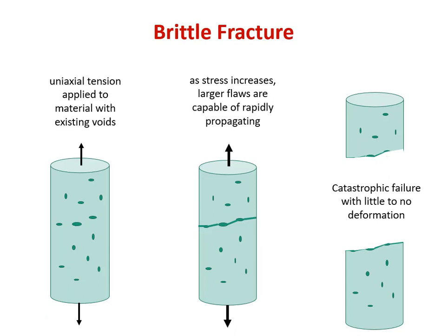we had catastrophic failure with little to no deformation, no warning, and more importantly, no other mechanism for absorbing energy. We put in mechanical energy from our Instron. The sample absorbed it elastically, so the total energy absorbed would be the resilience alone, that triangular section on our stress strain curve under only the elastic section. And at some point, before we could ever have any kind of plasticity or plastic deformation, before we moved a dislocation or put in any kind of permanent deformation, a couple of those big flaws reached a point where they could spontaneously propagate and the whole material failed.